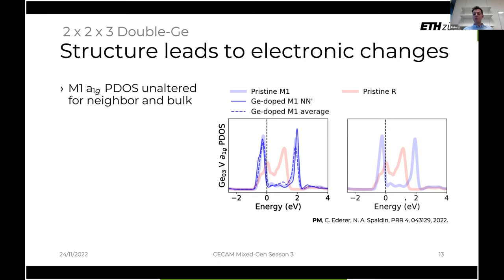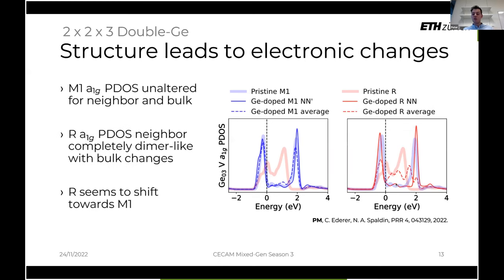However, in the rutile phase here, we see quite a striking change. We move away from the previous fully metallic phase that had a large amount of density of states at the Fermi level, into something which for the nearest neighbor looks completely identical to the monoclinic phase. So we have a completely bonding-antibonding peak. So indeed we believe we are forming a dimer. And also the whole structure as an average becomes quite distorted from what it was before. With the severe depletion of states at the Fermi level, we see that this rutile phase seems to be pushed towards the monoclinic one.